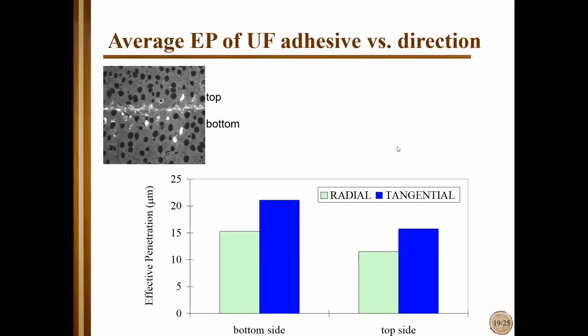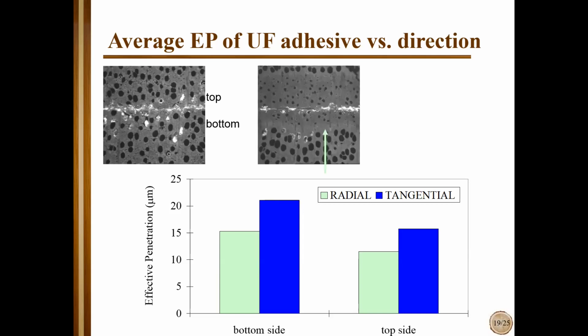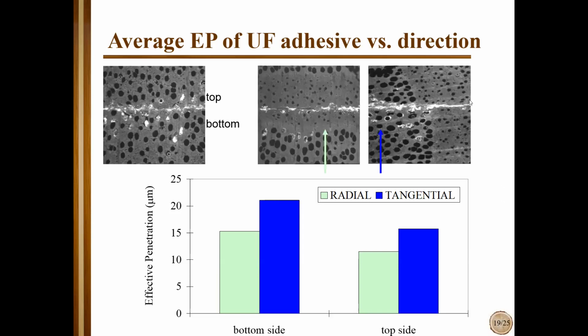A few other observations. It is important on which surface you apply adhesive. On the bottom surface where you apply adhesive, adhesive has longer time to penetrate. So typically it's deeper penetration than on the top side, where adhesive is only transferred when we put together 2 pieces of wood and place it into a hot press. There is also a difference in radial and tangential direction of penetration, especially in radial it was a bit lower than in tangential direction.